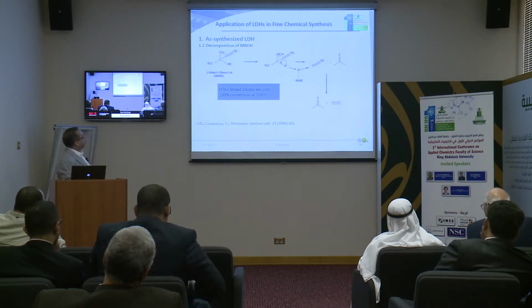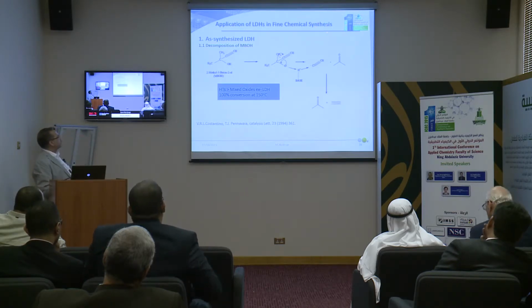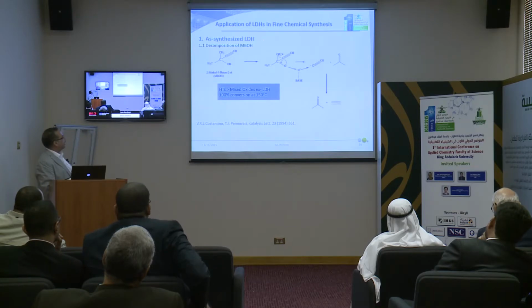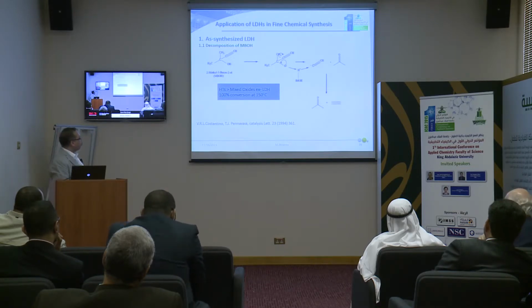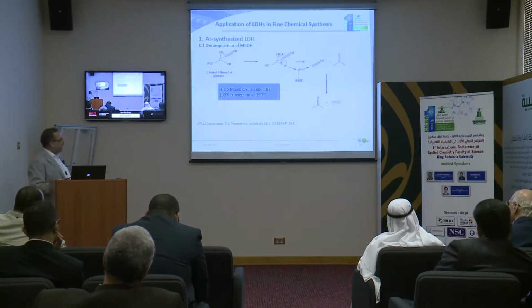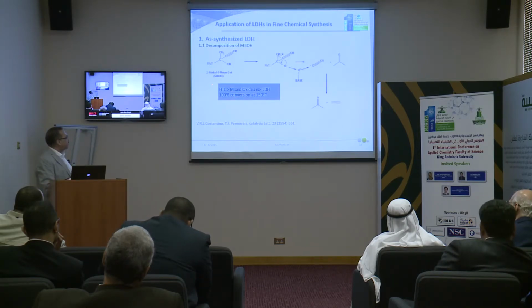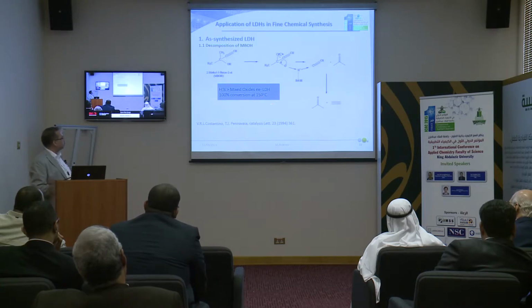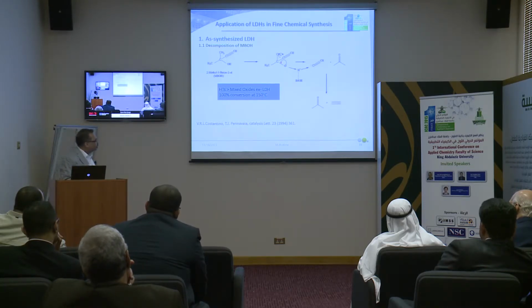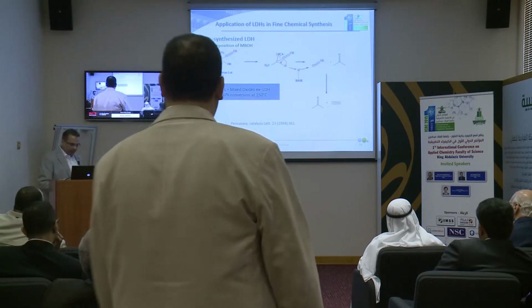For the applications of layered double hydroxide in the sense of fine chemicals, the as-synthesized material is found to be better than the mixed metal oxide or the layered double hydroxide, and gave 100% conversion at 150 degrees centigrade for the methylbutynol into acetone and alkyne.